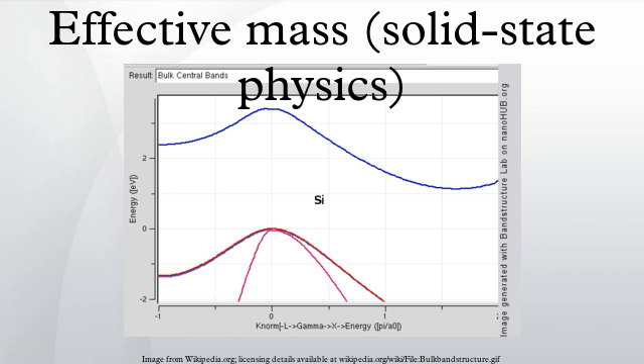Effective masses can also be estimated using the coefficient γ of the linear term in the low-temperature electronic specific heat at constant volume. The specific heat depends on the effective mass through the density of states at the Fermi level and as such is a measure of degeneracy as well as band curvature. Very large estimates of carrier mass from specific heat measurements have given rise to the concept of heavy fermion materials. Since carrier mobility depends on the ratio of carrier collision lifetime to effective mass, masses can in principle be determined from transport measurements, but this method is not practical since carrier collision probabilities are typically not known a priori.